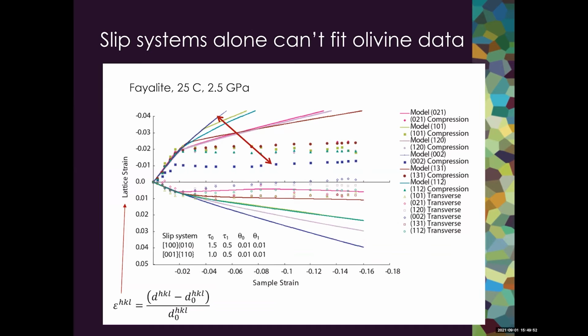So this is just an example of starting out with EPSC modeling for fayalite. This is a graph showing the lattice strain on the vertical axis, which is just the change in d-spacing relative to the first diffraction data point. And this lattice strain is plotted as a function of sample strain. The lines on the plot are the EPSC model, which correspond in color to the diffraction data here as the data points.